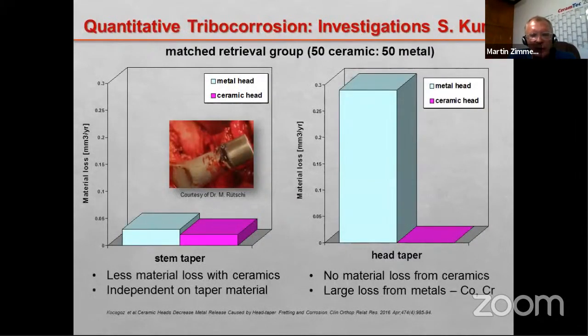We refer again to the study by Steve Kurtz, the same study done before with 50 ceramic heads and 50 cobalt chrome heads. Now they analyze in more detail the loss of material coming either from the taper of the stem, on the left-hand side, or from the taper of the head, on the right-hand side. It was clear from this picture that most of the material loss comes from the ball head, about 10 times more than the material loss from the taper of the stem.